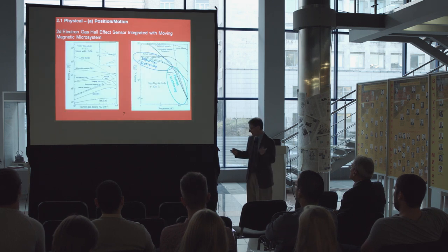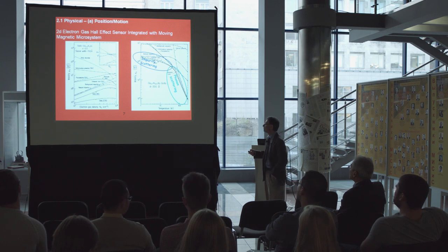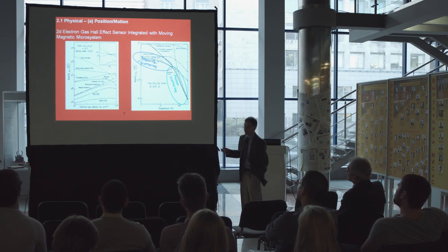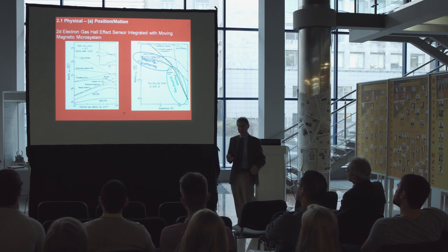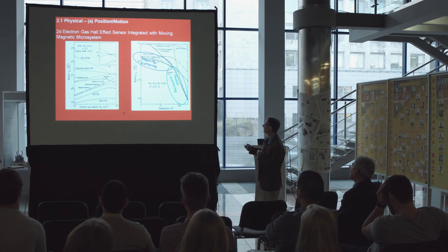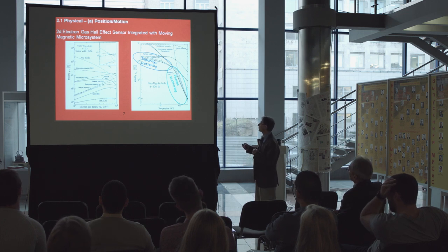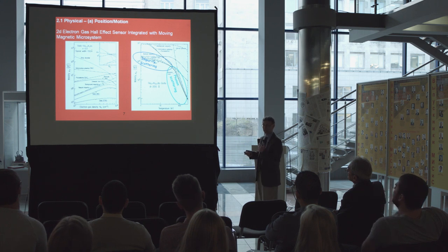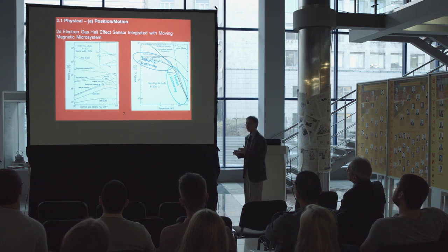So this is from that paper I told you about, those papers many, many years ago. This is a theoretical paper we did, so we looked at the effect on mobility of various things. The background impurities, if I have any extraneous impurities, things that I don't want there, they're extremely effective in lowering the mobility. So if I can lower the background and at the same time use the remote impurities to transfer carriers and get me this gas density, then I can get extremely high mobilities. And if you look at it at low temperatures or even moderate temperatures, you really just want to be phonon scattering limited, not deformation potential acoustic phonons, but piezoelectric phonons.